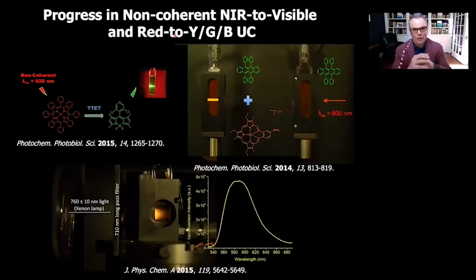But then, of course, to get to some of the things we wanted to get to, we were also, in parallel, really fascinated with whether we can do near infrared to visible photon upconversion, because that had never really been done before. A couple of the ways we recognized this was slow and steady. New BODIPY dyes, this particular one was made by one of my colleagues at NC State. This does not actually pi stack. So you can use massive concentrations of this, and look at that beautiful upconversion from this molecule. Again, you just have to get creative about the donor acceptor pairs that you use.